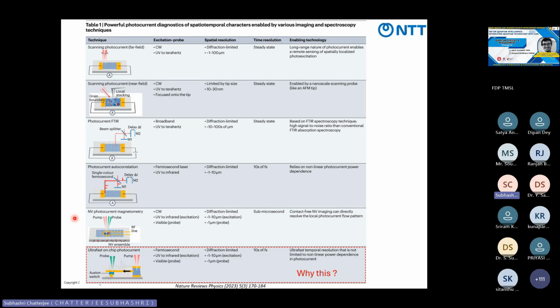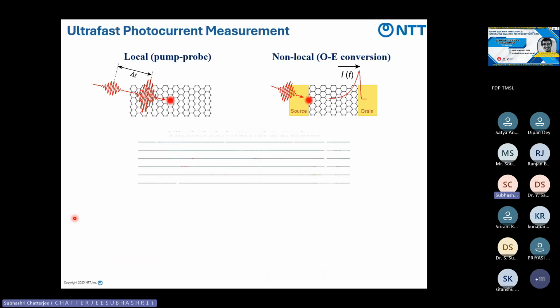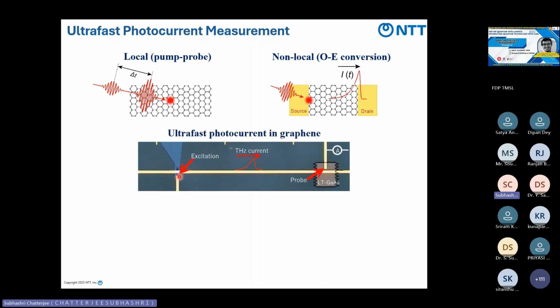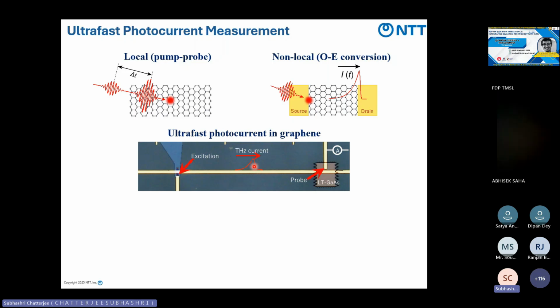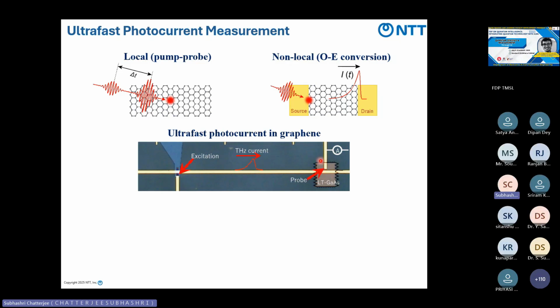When we shine the 280 femtosecond laser, we get a very fast signal. So if we understand this decay, like shining here and a terahertz current is generated, this decay time is very important. If we understand the decay time and compare the mechanism with available theoretical mechanisms like photovoltaic, photothermoelectric, bolometric, or nonlinear shift current, then we can understand how photocurrent generation is happening in this device. And if we integrate with other circuitry or electronics, then we can get a fast signal.